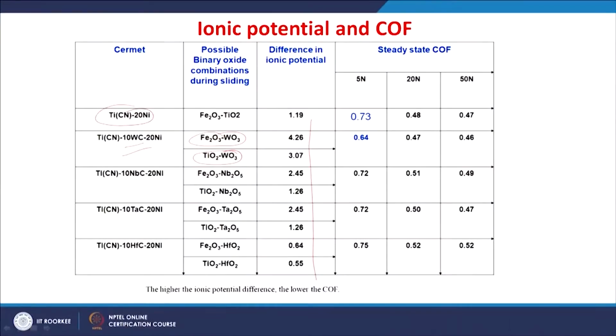Now, you see here, particularly at the lower load conditions, the higher the ionic potential difference, the lower is the friction coefficient. You can see the higher the ionic potential difference, the lower is the friction coefficient. The lower the difference in ionic potential, the higher is the coefficient of friction. But actually this behavior is not observed at a higher load regime.